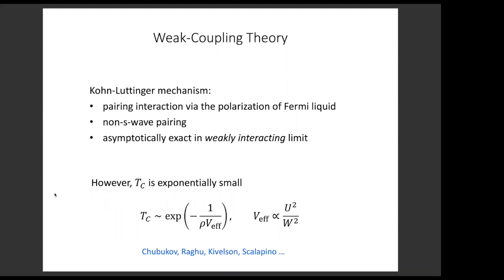Of course, the problem is that in that scenario, the Tc is exponentially small. Not only is it exponentially small in the interaction, but the pairing interaction itself is a second order effect. It's proportional to the bare repulsion squared divided by the bandwidth squared. So this will only give rise to a very small Tc compared to the Fermi energy.